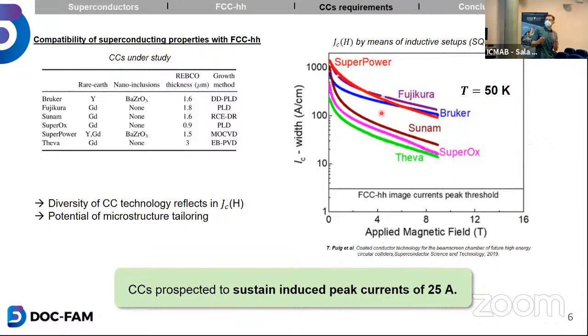As I mentioned previously, they are all REBCO, so rare earth barium copper oxide superconductors. And in fact, we are only probing the superconductor, not the metallic substrate or anything, because it's again a surface sensitive technique. However, the microstructure of all the coated conductors is quite different, because also the growth techniques of all the coated conductors are different. The entire architecture is different. They might use different buffer layer templates. They might use different growth temperatures. Sometimes they use different substrates, or they use even different precursors. And all of this influences, of course, the growth of the material.